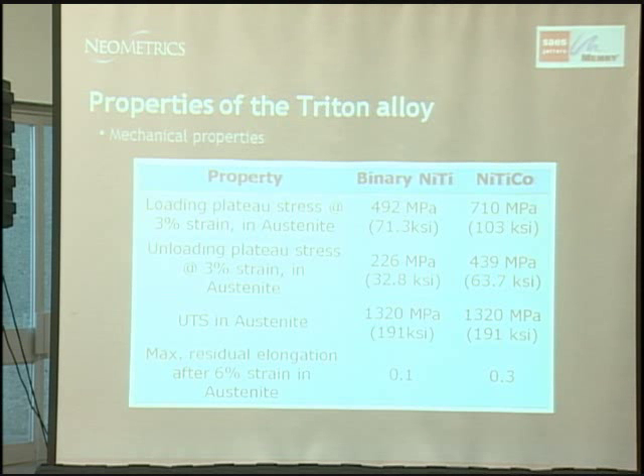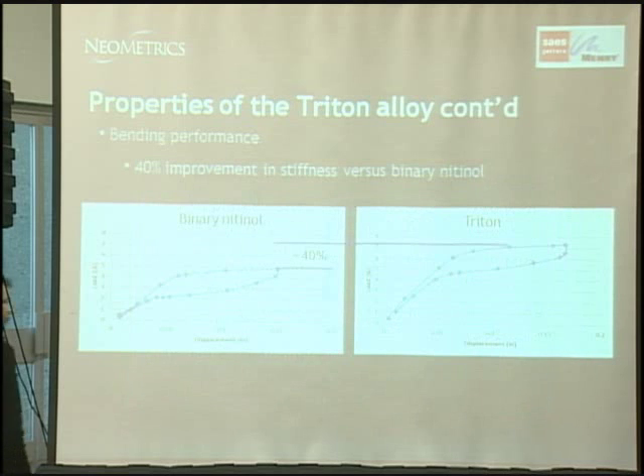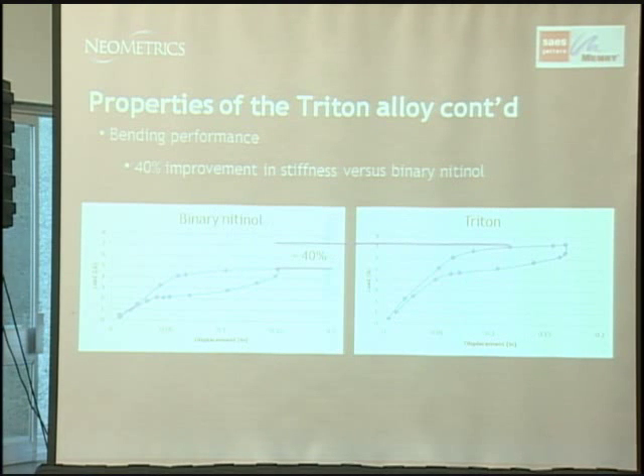The unloading plateau stresses coming from the hysteresis curve are 226 for nitinol and 439 for the cobalt nitinol. So you can see across the board the stiffness properties of the material, both in loading conditions and unloading conditions, are considerably higher than binary nitinol. This is the typical 3-point bend test with the hysteresis curve. If you look at the two loading curves side by side, you can see that the peak loading forces are about 40% higher.